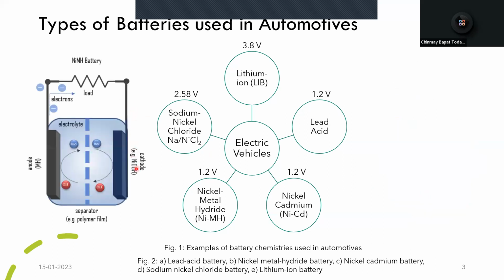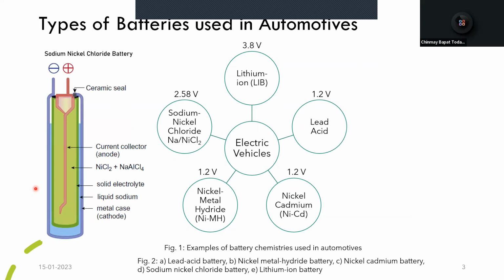For the nickel metal hydride battery, the cathode and the electrolyte stay the same, but the anode is an alloy of a hydrogen absorbing kind. For example, it is a combination of transition elements such as iron, nickel, cobalt, and rare earth elements such as lanthanum, cerium, etc. For sodium nickel chloride batteries, we have sodium metal as the metal casing and the cathode, and nickel metal as the anode. For the electrolyte, we have a combination of nickel and sodium conducting salts. And we have a ceramic sealing and a ceramic tube as a separator because of the high temperature of more than 300 degrees Celsius, that is the operating temperature for these batteries.